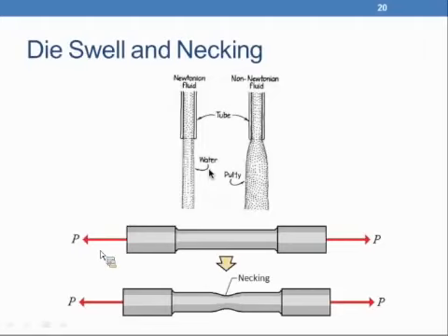We attempted to alleviate some of the necking effect by using a fan to cool our filament just as it left the nozzle, in an attempt to freeze the material before it had a chance to elongate. What we found when we did that was that the fan, although it froze the filament and stopped the necking, caused the die temperature, which you can see on the bottom display, to drop drastically. We were operating around 170 degrees Celsius, which will work, but that caused the die pressure to increase. Because the die was colder, the filament had a harder time squeezing through, increased the pressure in the system, and when the pressure increases in a system, the die swell percentage increased. So our attempt at stopping necking caused our die swell to increase. We ended up creating a product that had almost 3 millimeter diameter filament because of the increased pressure in our system.